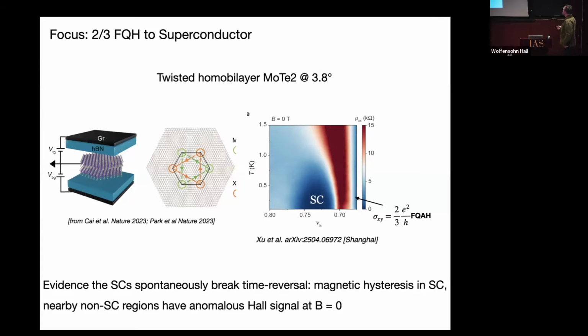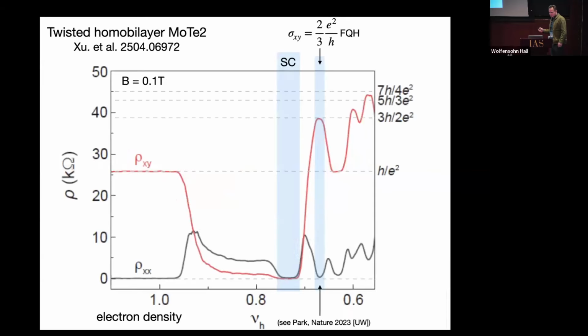And then as the samples improve this summer, there's this kind of amazing phase diagram. This is at zero magnetic field. Conductivity as a function of temperature and the electron density. When you fill at 2/3 filling, you get this quantum Hall effect, so there's zero resistance. Then as you dope that 2/3 quantum Hall effect, there's a phase transition into a superconductor. And there's good experimental signatures that this superconductor is also a ferromagnet of some form. It sort of inherits the same time reversal symmetry breaking as the nearby quantum Hall effect.